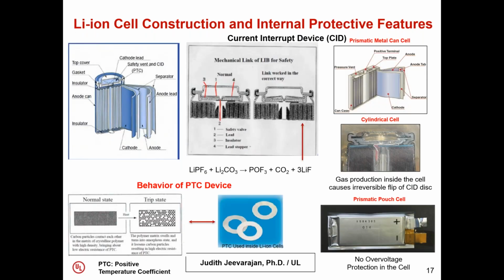Lithium-ion cell construction, as I said, is of three main types: the cylindrical, prismatic metal can, and the prismatic pouch formats. With the metal can cells, there is an internal protective device, called the current interrupt device, or CID, that helps under overvoltage or overcharge conditions. The way the device works is that when the voltage of the cell increases, there is an additive, lithium carbonate, that had been added to the lithium-ion cells. Above a certain voltage, this produces excess carbon dioxide, and the pressure inside the cell increases, thus moving the two discs of the CID apart.